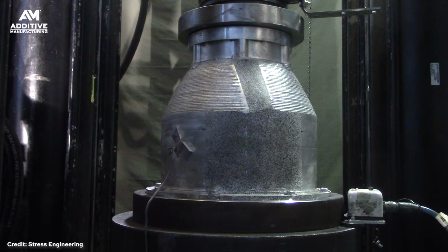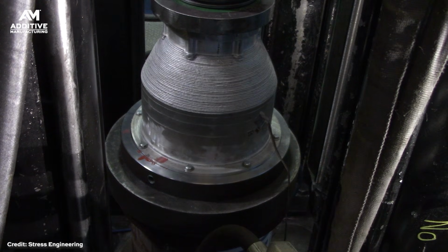We were able to apply over 4,500 psi, way beyond its designed internal pressure or pressure rating, to try to get the additive material to fail. And it still did not fail. In fact, even with that, applying over 1 million pounds of compressive inload to counteract the pressure axial load, the additive material still did not break or leak or crack under the extreme hoop stress that was coming from the